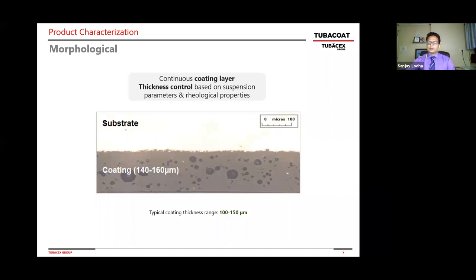So this coating is a continuous homogeneous layer managed through an automated process, as I said, and through rheological suspension properties. In automatic control process, this coating is 150 micron, 0.15 millimeter, and we're able to control the thickness across the length of the pipe with the same thickness, where we measure minimum at the start, at the middle, and at the end, and we get minimum, maximum, and average thickness properties, and we're able to control the thickness in a very unique way.